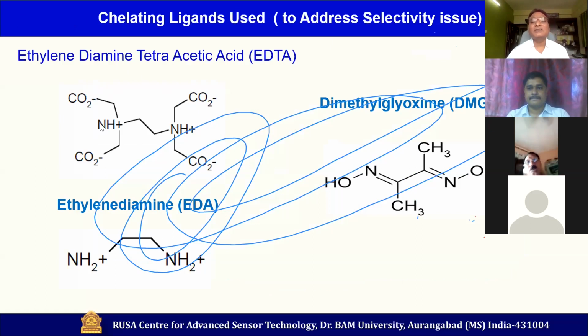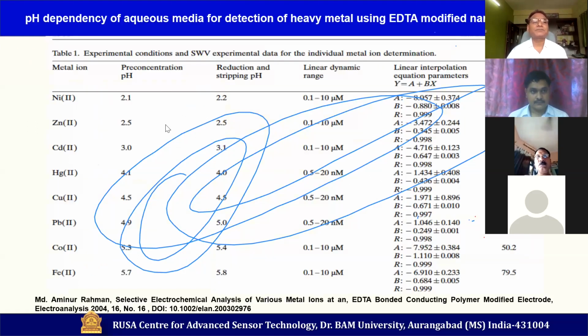These are some of the chelating ligands we are using for modification of this nanostructured composite material, right? EDTA is one, DMG is another, EDA is third. So these are three different chelating ligands we have explored so far for addressing the selectivity issue. Moreover, while going through the literature, and we have seen by doing experiments as well, that if you somehow could manage pH during